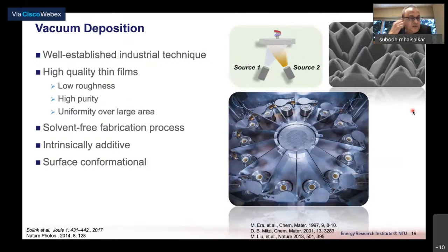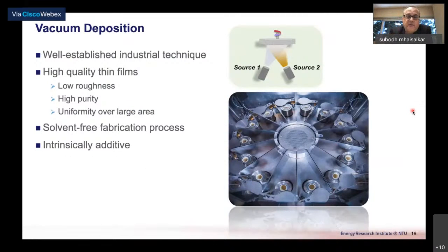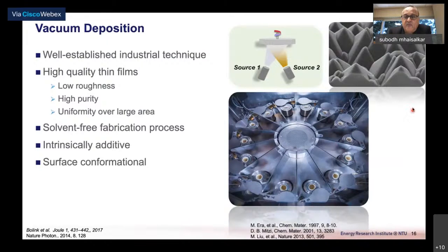So we began working on vacuum deposition primarily because at that point, one of the major challenges was conformal coatings on silicon surfaces that have been really tuned for maximizing essentially optical control. The other major advantage of evaporated materials is they are free of solvents. And if they're free of solvents, the argument is they should be more stable than solution processed materials. And we will investigate this factor later on.